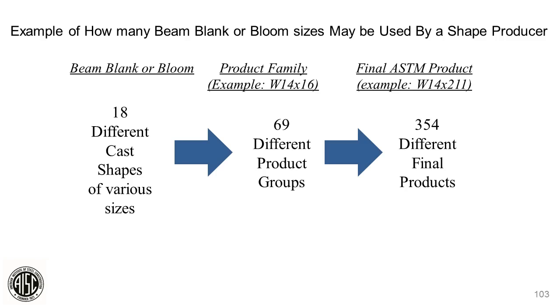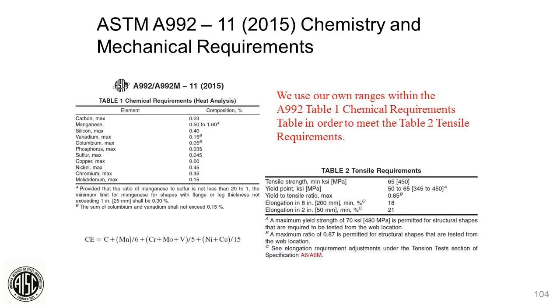This is an example where you have 18 different cast shapes, beam blanks for example, and that would go into maybe 69 different product groups, and you might end up with 354 different final products. Next. If you look at the A992 specification, it looks wide open, but you can't use the same chemistry for a W6x15 as you would for a W14x370. So you want to use different chemistries for different products. Next slide.